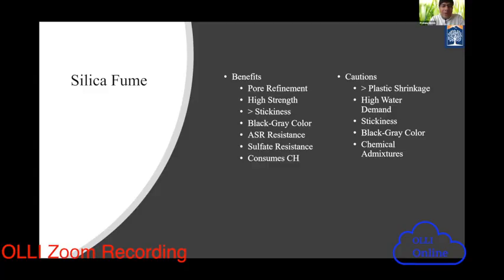So what are the benefits? Heavy amount of pore refinement. This time you are going to generate the strength from the very beginning heavily. So when you replace silica fume with cement, then you start to get very high strength from the beginning. Not only in the beginning, you are going to get long-term strength also. So that is the biggest advantage of the silica fume compared to fly ash and slag. Fly ash and slag provide a little bit low strength initially, then they catch up and exceed the original cement strength. But silica fume in the very beginning provides very high strength.